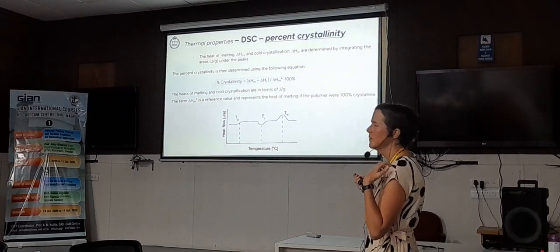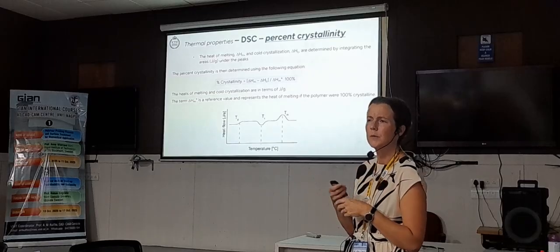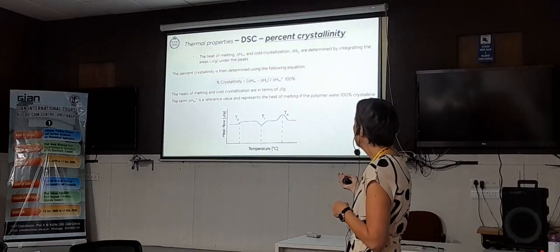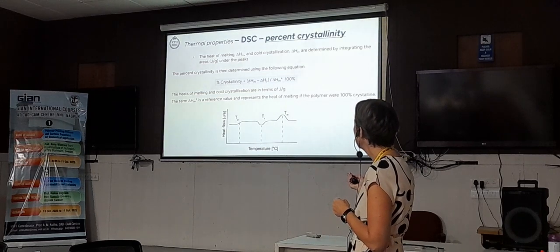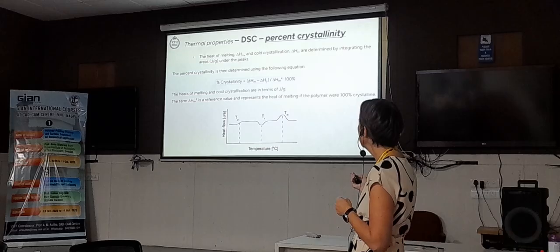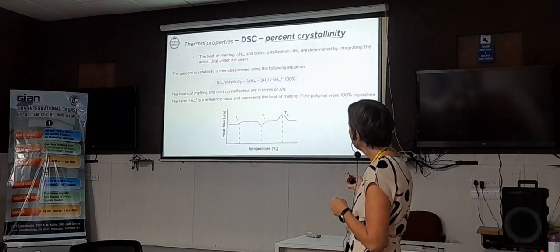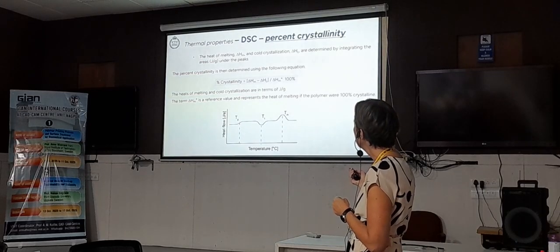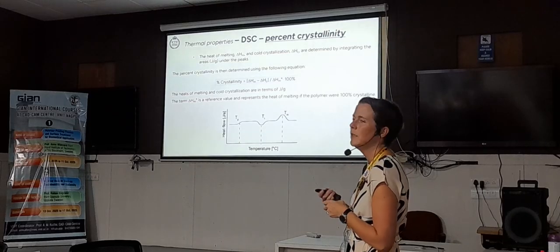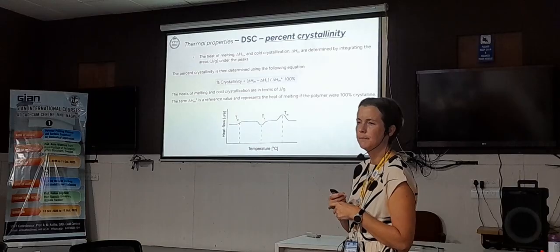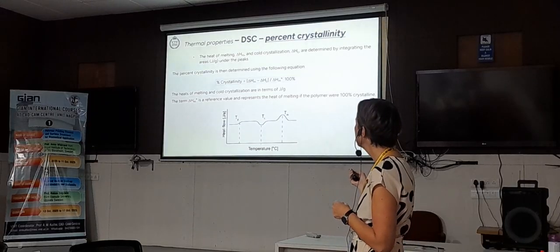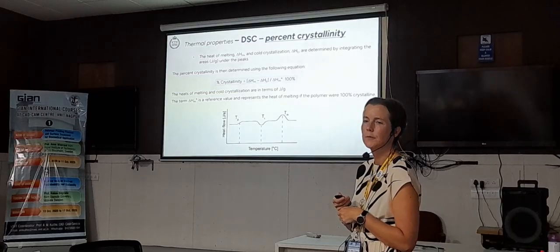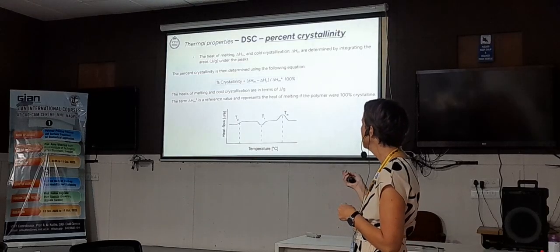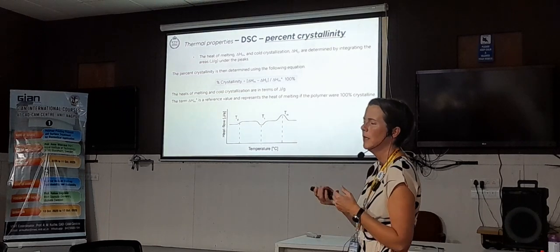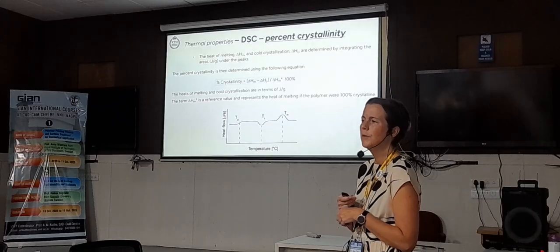And looking at this DSC curve, if you have a semi-crystalline polymer, you can also calculate the crystallinity, which we also normally report, and which is also good to compare between different polymers. What you then do is take the area under the melting peak, subtract the area under the crystallization peak, and then divide it by the value of what it would be if it was 100% crystalline. Those values you have tabulated for most polymers. You can find that.